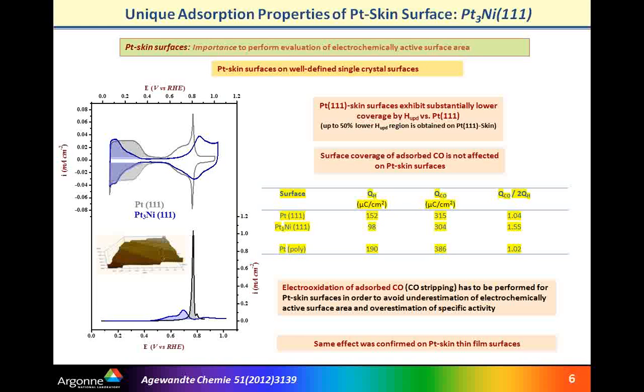This is just one example which shows, in the upper part on the left-hand side, the adsorption of hydrogen. Usually people in fuel cells are using adsorption of hydrogen as a measure for the number of active sites. Certainly this is very convenient if, as in our case, we have single crystal surfaces, but Boya would demonstrate clearly that this is almost impossible to use in the case of high surface area materials. So we developed another method, where we were trying to establish the number of active sites based on CO stripping voltammetry, which is shown on the bottom of the left-hand side slide.